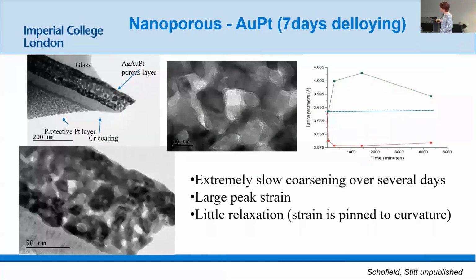So this is some TEM imaging of one of those structures, and you can see it's crystalline, so you can see some lattice imaging. You can see the porosity length scale of this is about 5 nanometers. But that's showing up really badly. But this is the strain that we extract from the diffraction. And you can see it's enormous. And it doesn't really ever relax back down to normal. So these materials stay very highly strained over time. The strain is pinned to the curvature. Right? So if you maintain the morphology, you maintain the strain in these systems.